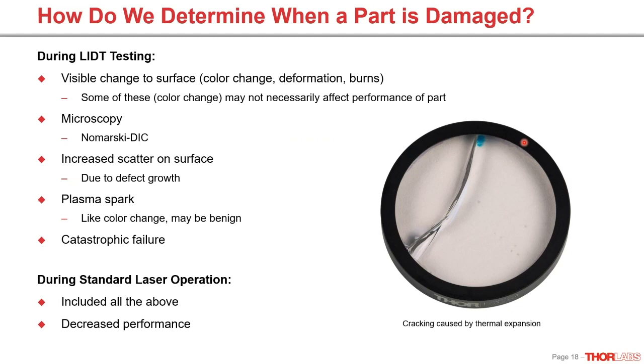Also, parts are often inspected with Nomarski DIC microscopy, and that's just to get a good contrast and high zoom. This can be done either in situ or afterwards. Obviously, it's easier to have your damage detection be online rather than put some pulses on a part, remove it from the setup, check for damage, and put it back in. So that's typically something to be avoided.